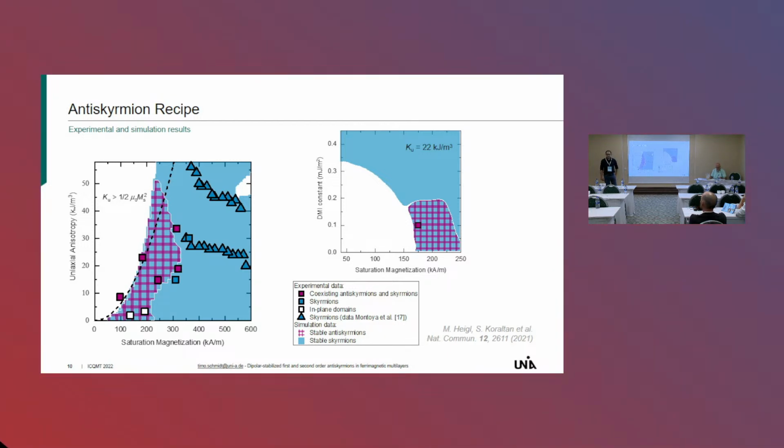Also, I remember Eric Fullerton was telling me that in that system they saw a 3D structure. So in the middle, there's a Bloch skyrmion, and then there's a Néel cap on top and bottom. Do you see any depth-dependent variations of the spin texture? Could you explain it a little bit? Their system is without this iridium, it's just the iron gadolinium, and typically you see the Bloch skyrmion, but there's a Néel cap.